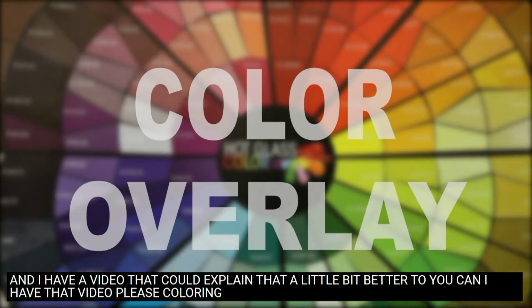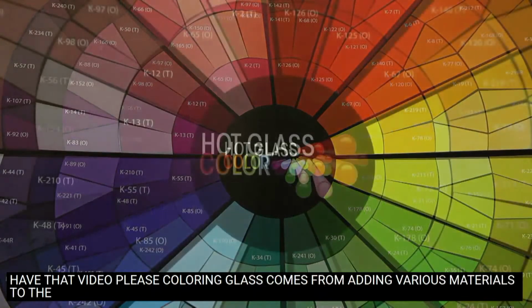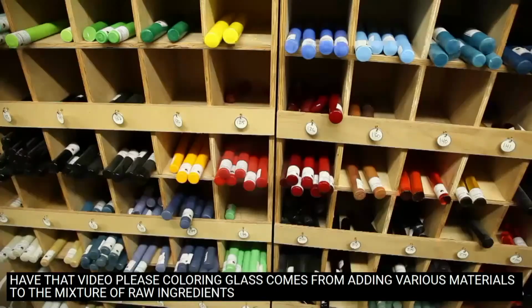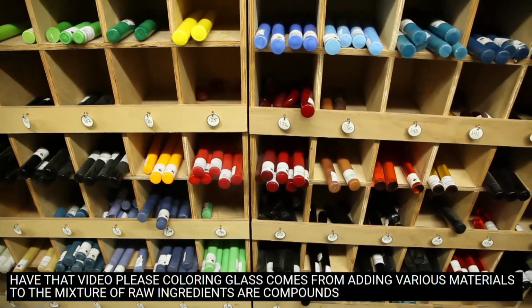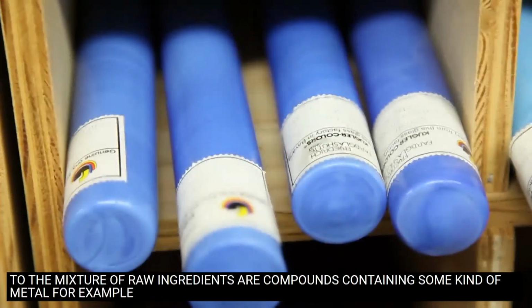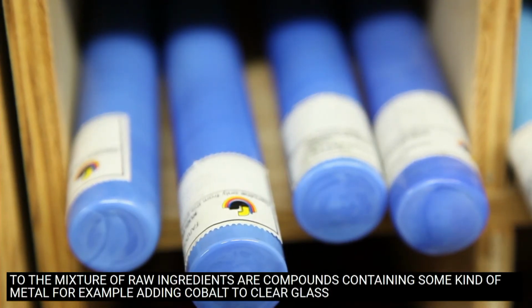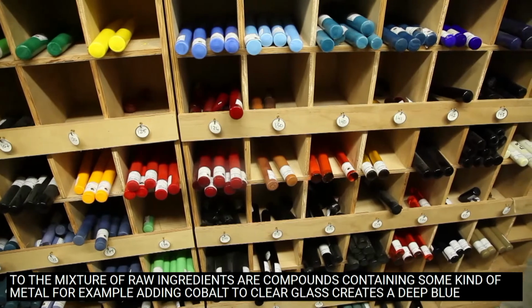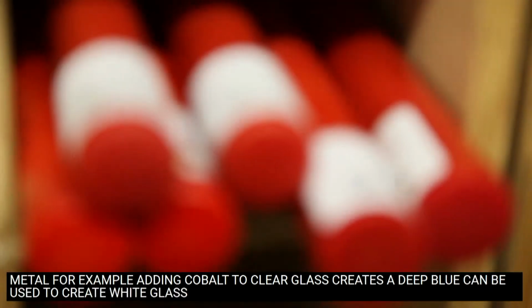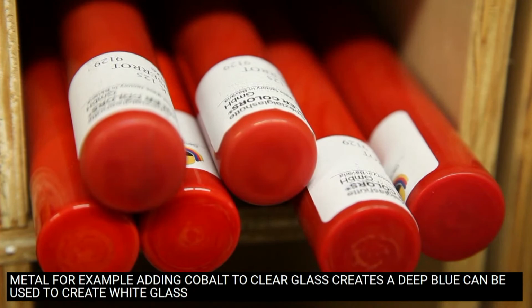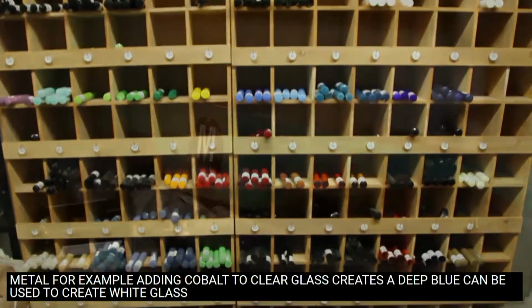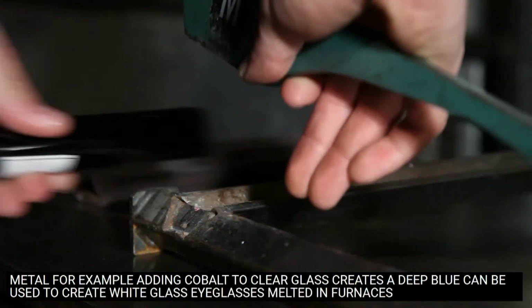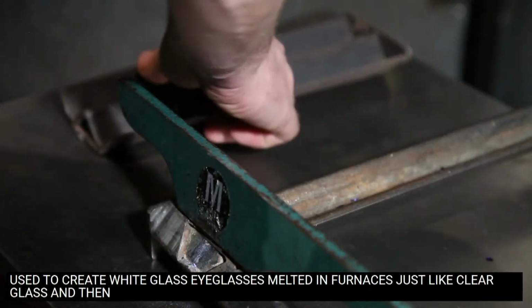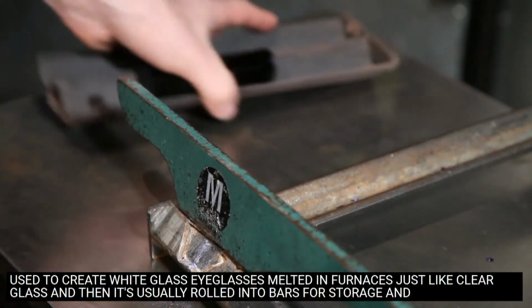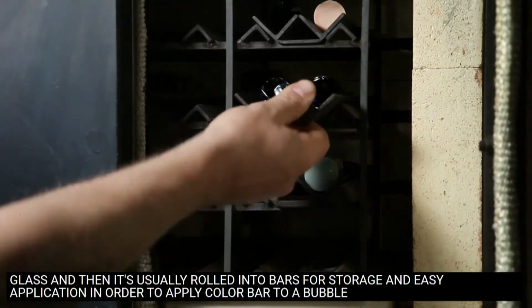The color in glass comes from adding various materials to the mixture of raw ingredients called batch. Most of the colorants are compounds containing some kind of metal. For example, adding cobalt to clear glass creates a deep blue. Tin and antimony can be used to create white glass, and gold chloride can produce a rich red or pink colored glass. Colored glass is melted in furnaces, just like clear glass, and then is usually rolled into bars for storage and easy application.